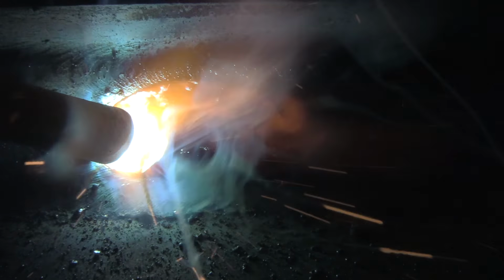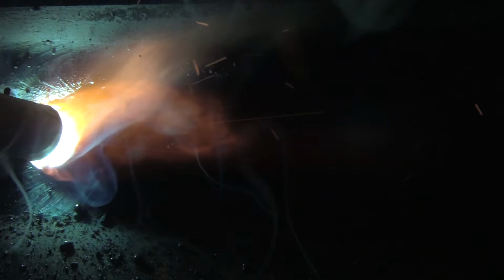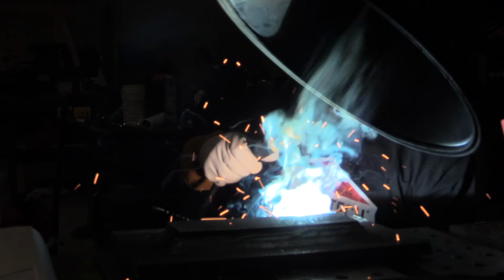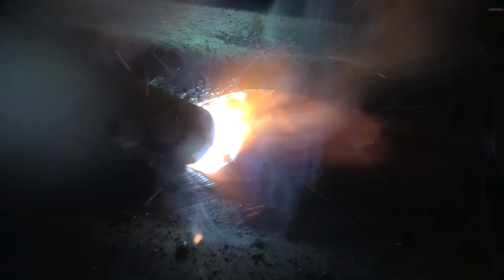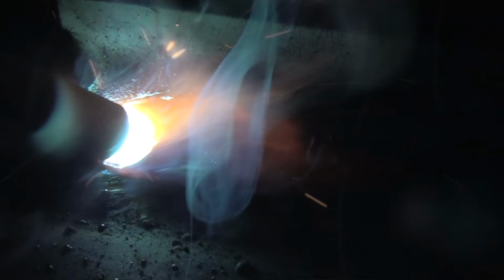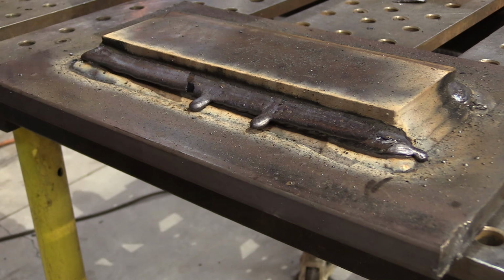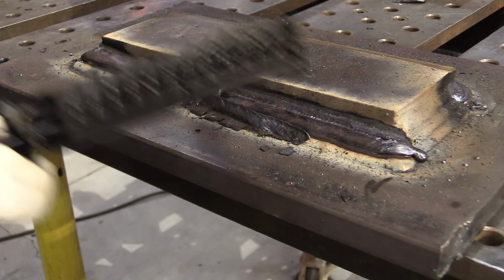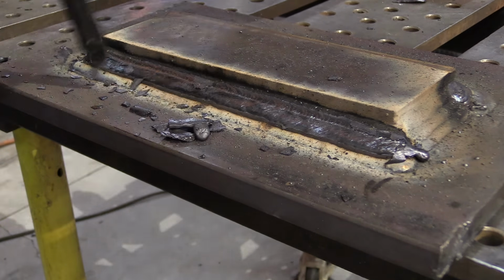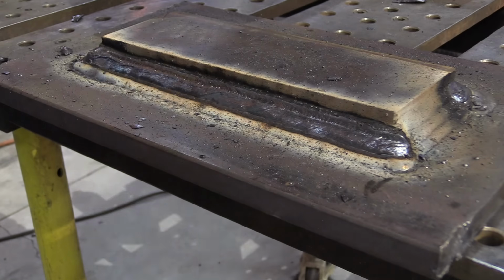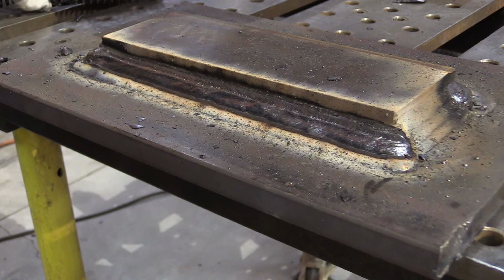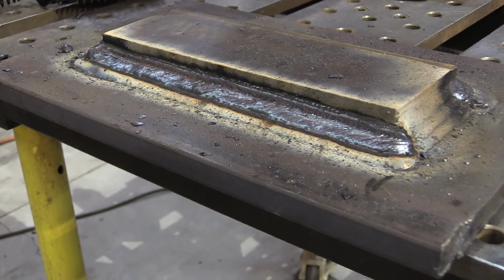On the second pass of this 3-pass multi-pass fillet weld, it also did a pretty good job. I've got that crowned up bead on the bottom kind of supporting the molten slag there, and so it did a pretty good job. I'm just trying to drag it along with a nice tight arc, almost letting the metal support part of the weight of that rod, and I'm just not doing anything a whole lot different than I was with the 7018 in the previous video. We'll chip this off now, and it also looks pretty good, pretty smooth ripples, but I did notice a little bit of a ridge in the center of the bead that I didn't notice on the previous bead. So it's already starting to have an effect. Gravity's already starting to have a little bit of an effect here.